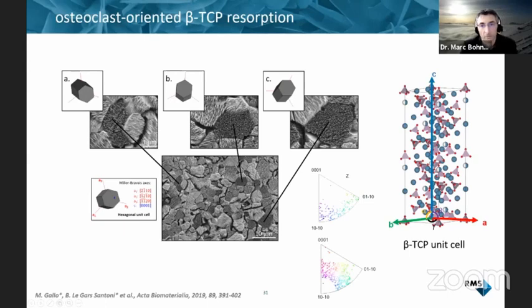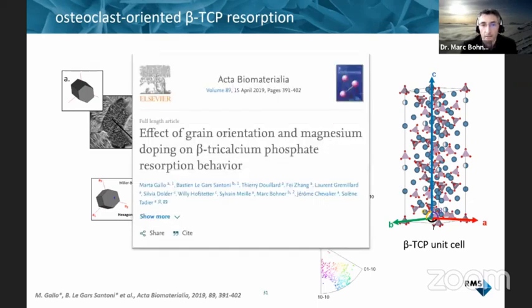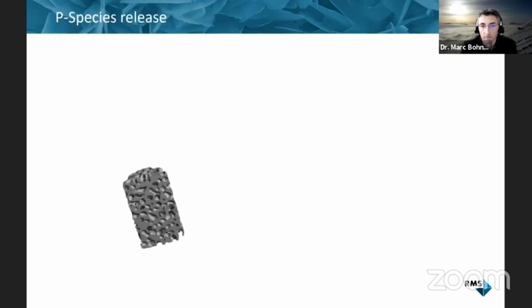I would like to have a few concluding remarks. To say that we had a collaboration with Martha Gallo and the group of Jérôme Chevalier and Solène Tadier in Lyon. They were interested in trying to identify the direction of these needles that we find by osteoclastic resorption, and they found that they are aligned according to the C-axis of beta-TCP, and they also had a look at the effect of magnesium on this and found some interesting changes due to the presence of magnesium. This is the paper that I'm talking about.